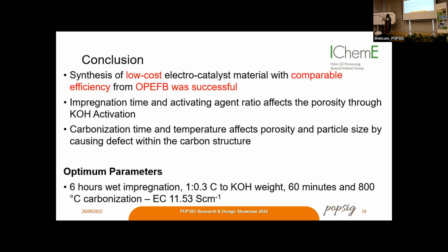And it was found that the impregnation time and activating agent ratio affect the porosity through KOH activation. And lastly, carbonization time and temperature affect the porosity and the particle size by causing defects within the carbon structure. So the optimal parameters to obtain the best electrical conductivity and nanoparticle are 6 hours of wet impregnation, 1 to 0.3 carbon to KOH weight ratio, 60 minutes and 800 degrees of carbonization to obtain 11.53 Siemens per centimeter electrical conductivity.